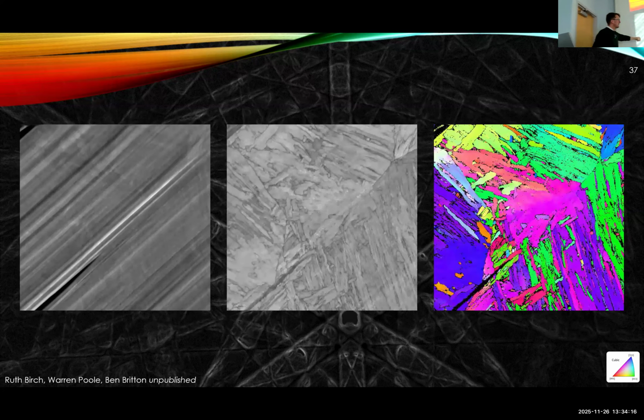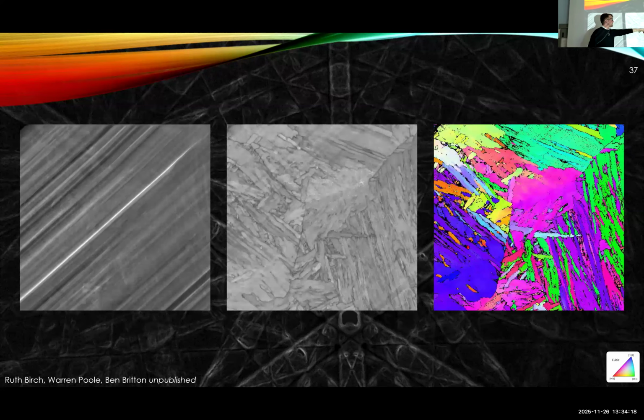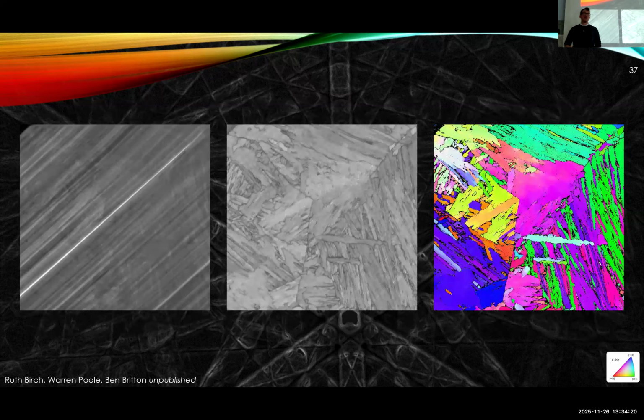And this is what happens as you're reading the book in the microstructure. So we're going through. This is the surface. This is the band contrast. This is then the microstructure as indexed of that. So we can start to see that emergence of the 3D microstructure to start looking through that object.